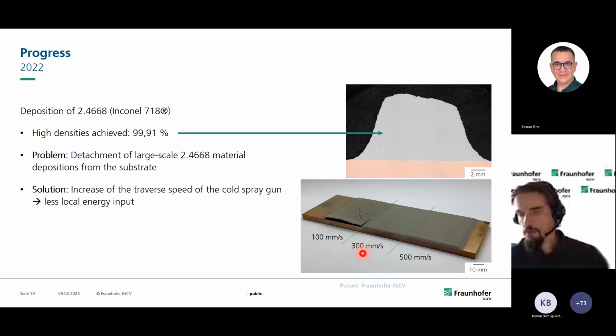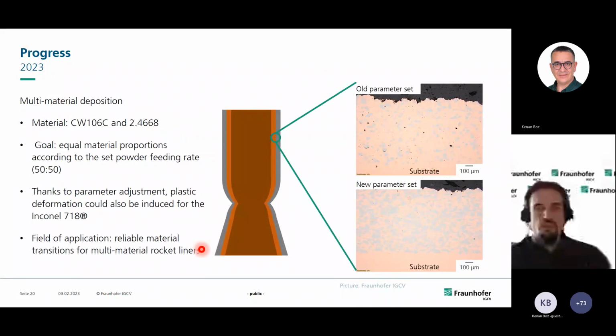And the 300 millimeters per second weren't even enough during the specimen preparation. These also cracked away. But with the 500 millimeters per second, we managed to get a good bonding to the substrate, which is actually one of the key features you need for processing multi-material, of course. And yeah, that's where we are now, where we want to go.